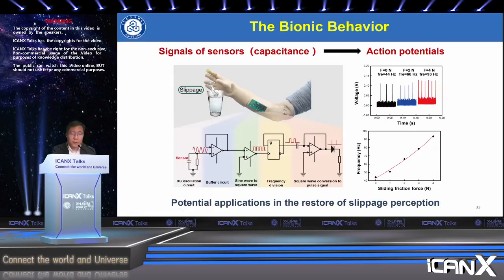And to regenerate the slippery perception for these neuroprosthetics, a signal encoding circuit was designed for bionic stimulus response signals, which is helpful to transmit the analog signals, such as the capacitance, from the sensors to the nerve tissues. According to this signal encoding circuit, the frequency of the resulting bionic pulse signal was modulated by the applied sliding friction force. From this figure, we can see the signal response under different sliding friction loadings: the spike frequency increases as the capacitance decreases due to the slippage. So through this design, the circuit, the frequency range and the variation trend of the sensors are able to achieve a result similar to the human response to the force stimulus, which can potentially be applied to restore slippery perception in neuromorphic systems.